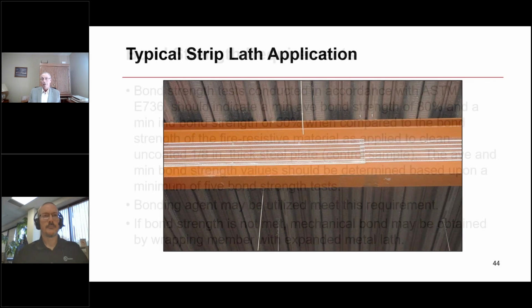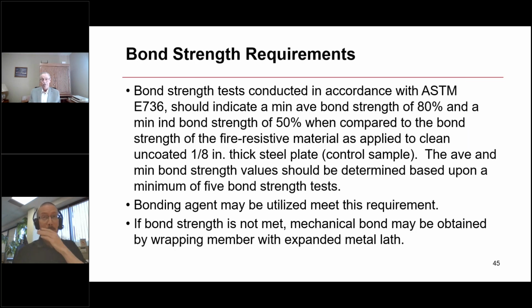Now, the second requirement to use hand in hand with those dimensions that we've just gone over is a bond strength test. If you have an unknown primer, you need to conduct bond strength tests of the spray applied material as applied to that primed steel. And the results of testing in accordance with ASTM E736 should indicate a minimum average bond strength of 80% and a minimum individual bond strength of 50% when compared to the bond strength of that same material applied to a clean, uncoated 1/8-inch thick steel plate. In other words, a control sample. And the average and minimum bond strength values shall be determined based upon a minimum of 5 bond strength tests.